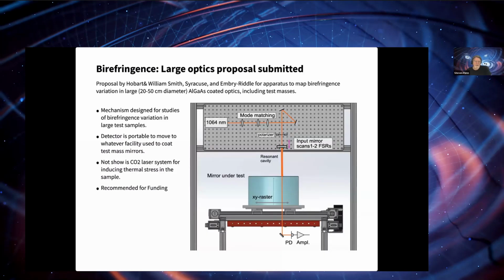And a proposal was put in by me and Stefan Ballmer at Syracuse and Andre Gröderson to study the birefringence on larger optics. So this will fund the development and study of 20 centimeter AlGaAs optics and have the capability for measuring the birefringence and mapping the birefringence up to and including the test masses for both A+ and even could be extended for use for the test masses for Cosmic Explorer. This proposal has now been recommended for funding.